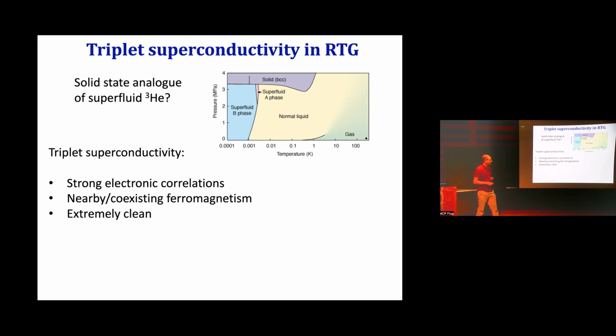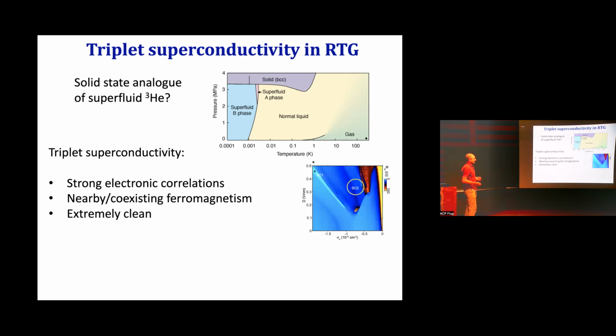Okay, you must have a very, very good crystal with very low density of defects. Defects will destroy this type of superconductivity, whereas they won't destroy a singlet superconductor, s-wave. Now, it turns out that in these graphene-based systems, all of these conditions are actually met. So in some sense, this is an ideal system to look for triplet superconductivity.